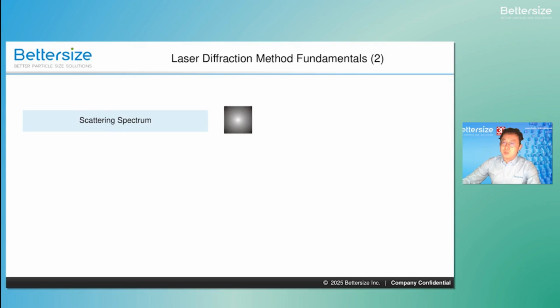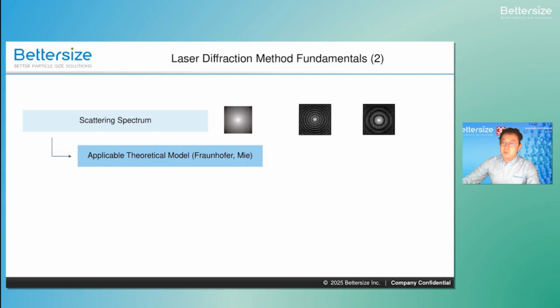So how do we turn that ring pattern into a graph? First, the detector captures the raw scattering spectrum, which is essentially a composite signal of light scattered by every particle in the chamber. To decode this, we apply Mie theory, which acts as a reference library to identify which specific ring pattern corresponds to which particle size.